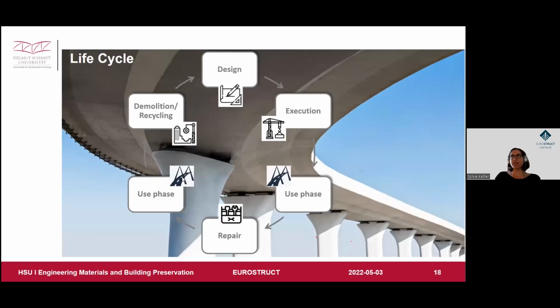So coming back to the life cycle, now we have understood the mechanism. Now we also know that probably the prescriptive durability design rules of the Eurocode are probably not the best way to ensure it. We have just another issue of the execution, because all the exposure classes design and all the probabilistic modeling relies on a perfect concrete, a crack-free concrete. We know that due to execution, we can have some problems with shrinkage, with any other issue which leads to cracking. And here I want just to mention any cracking, any concrete cracks would enhance this process of corrosion initiation and would just shorten the service life much more.